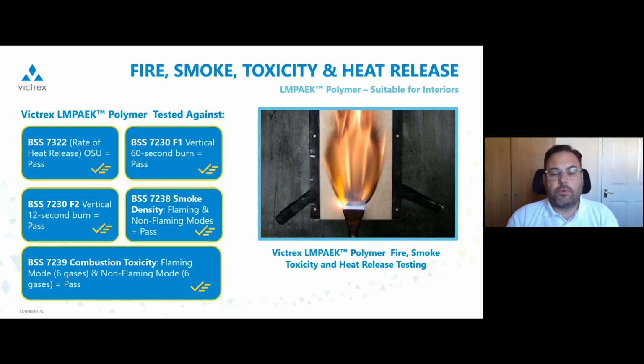Again, because having in mind that these materials go into an aeroplane, it's quite common that what we have listed here is some tests that we did on the LMPAEK polymer. So we would either make a plaque or films, again depending on the standards. We tested again the Boeing standards, but similar to the fire test standard, whether it's the Boeing standard or the Airbus standard, AITM standards, they are interchangeable. So when you pass one, you pass the other. So we tested the rate of heat release. It's also called OSU. I think it comes from the Ohio State University. Again, to see how much heat goes through.